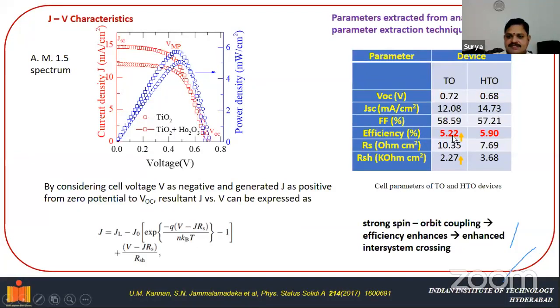For instance, if I consider the efficiency of the device, in the parent titanium dioxide based device, the efficiency that we have obtained is about 5.22, and in the HTO device we have obtained efficiencies of the order of 5.90. Now the question is, why is there an improvement in the efficiency of the device after we add holmium to the device? We have repeated this several times and we could see a similar, increasing trend after adding holmium to the titanium dioxide based device. The probable reason for the enhancement in the efficiency of the HTO based device can be due to the spin orbit coupling of the holmium oxide.